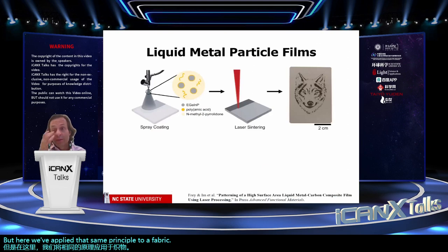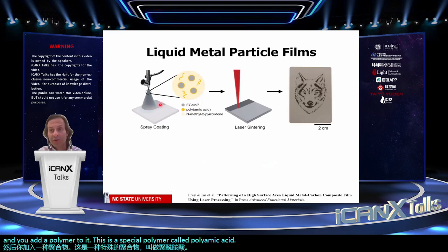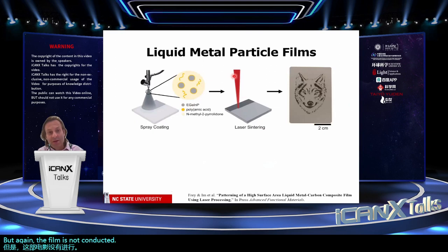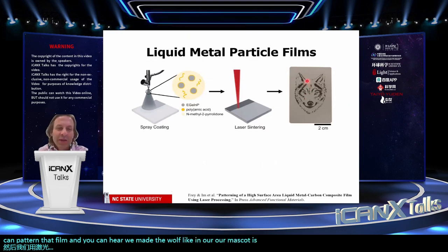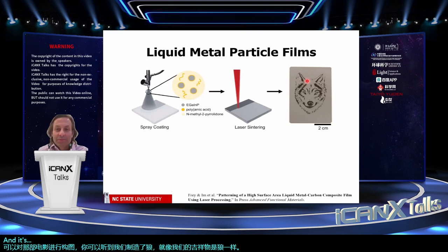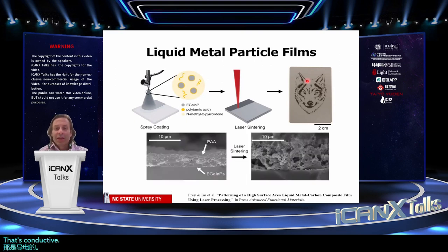And then again, this is taking advantage of particle films. If you take those particles and add a polymer to it, a special polymer called polyamic acid, we can simply spray it onto a surface and form a film. But again, the film is not conductive. So then we take a laser and we can pattern that film, and you can see we made the wolf, our mascot is the wolf, and that's conductive. And not only is it conductive, it makes the film have higher surface area.